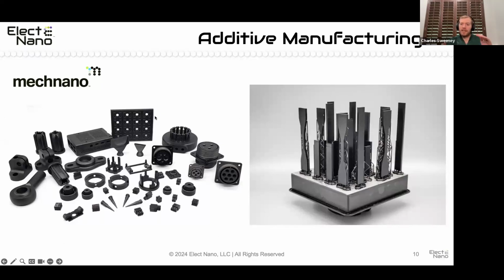And this is challenging because you're using light to cure the material, and carbon nanotubes are typically highly absorptive. Nanotubes absorb from DC to daylight, so you're battling this. I need to get light into the photocurable system in order to get it to cure, but I also can't have it be pure black, because that would quench all of my curing energy. So our team had to work really hard to ride the edge of the knife in terms of the process window, material functionalities, and grades of nanotubes that we work with to achieve this. But it's absolutely incredible when I see these parts, knowing that their incredible properties are coming from discrete carbon nanotubes that have been put into the system.